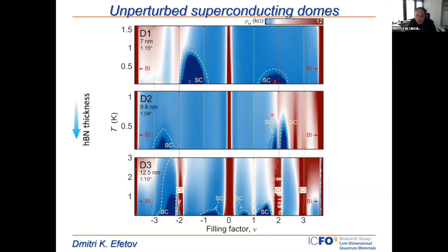But also what we know matters a lot is twist angle disorder, strain profiles, percolation paths. Because these superconductors are not homogeneous, there are maybe some different percolation paths for these. That's why we form Josephson junctions in devices where there are supposedly no Josephson junctions. So the systems are very disordered. My guess is that this trilayer system is maybe a little bit more stable because somehow the extra layer of graphene stabilizes these inhomogeneities. But this is just a guess at this point.